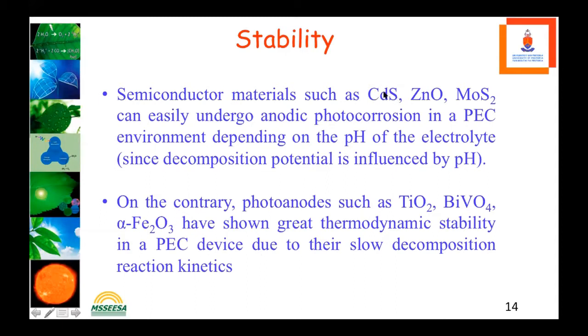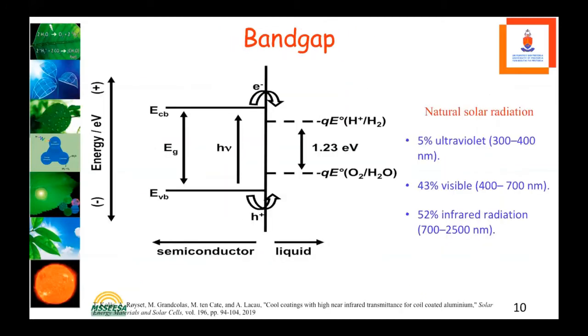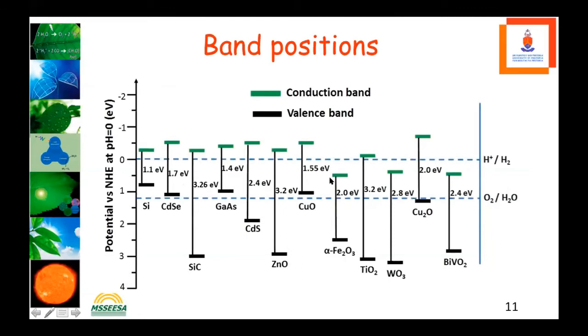Such chemical compounds like cadmium sulfide, zinc oxide, molybdenum disulfide can easily undergo corrosion in photoelectrochemical environment depending on their pH. And on the contrary, titanium dioxide, bismuth vanadate and hematite, this iron oxide, have shown great thermodynamic stability in a PEC device due to their slow decomposition reaction. Let me go back a bit and say something here, that if you look at hematite, it's 2 electron volts, and then the other ones that are considered efficient and better, bismuth vanadate is 2.4 electron volts.